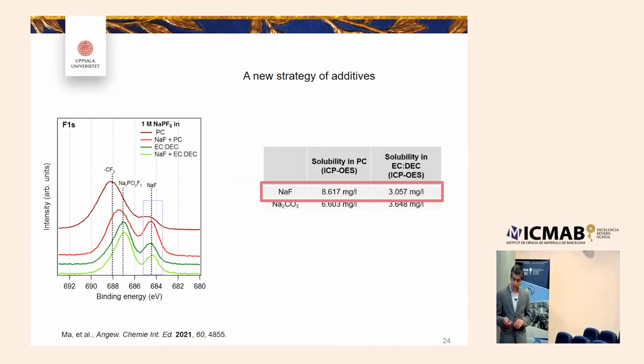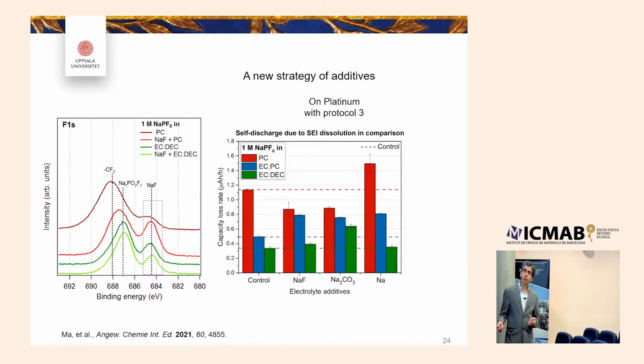So we could see from here that we expect the capacity loss to be smaller if we add sodium fluoride to PC, and that is exactly what we did. If you look at the red ones here, this is the control sample, and this is saturated by sodium fluoride. We can see there is lower capacity loss in the saturated sample. While if you look at EC:DEC, we don't see a major difference. Actually, it became a little bit worse when we added sodium fluoride to that electrolyte.